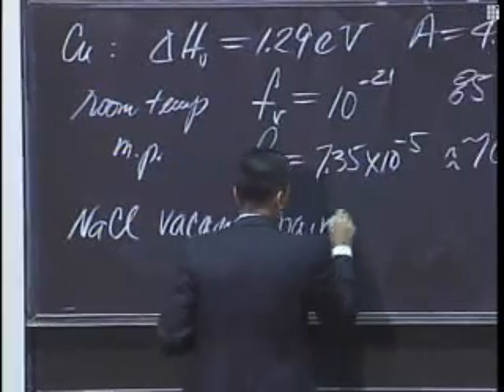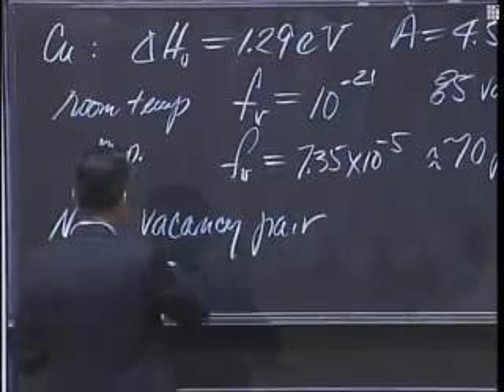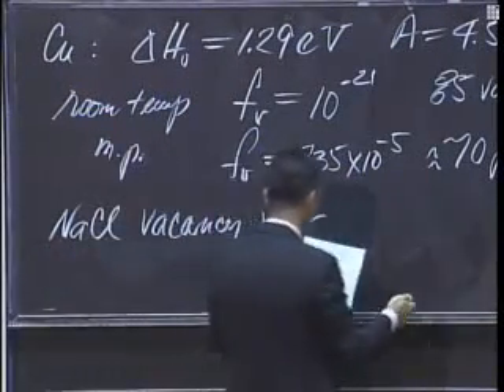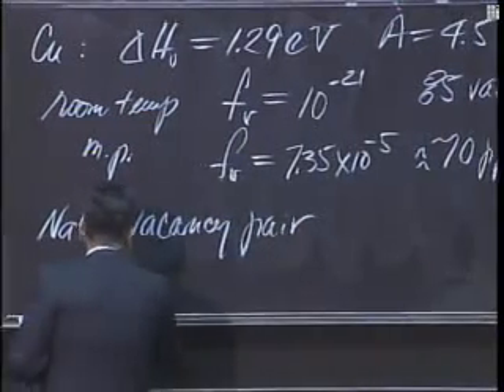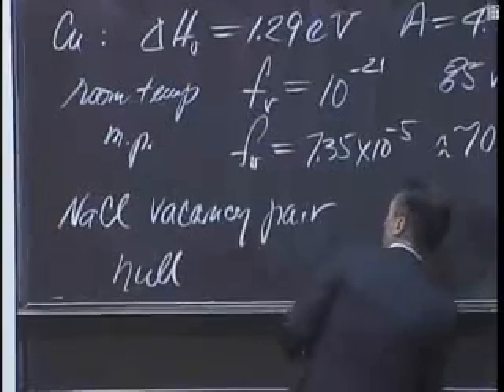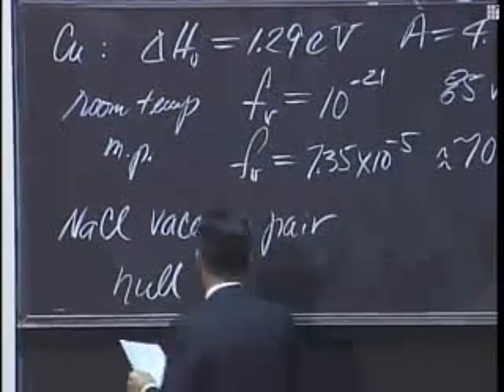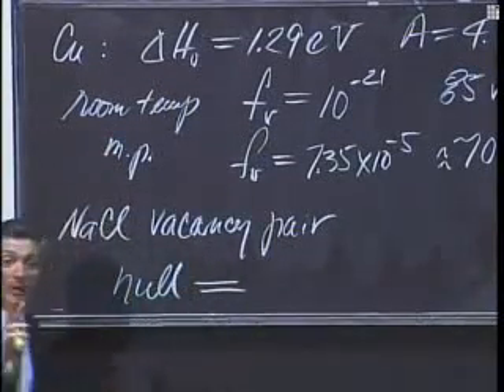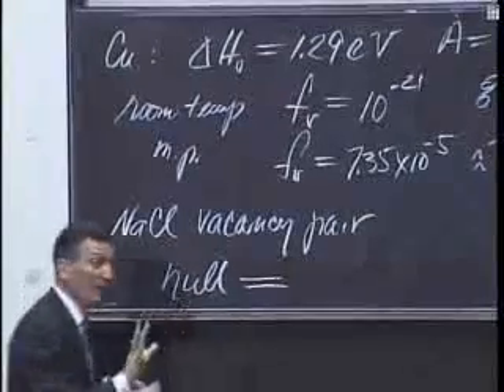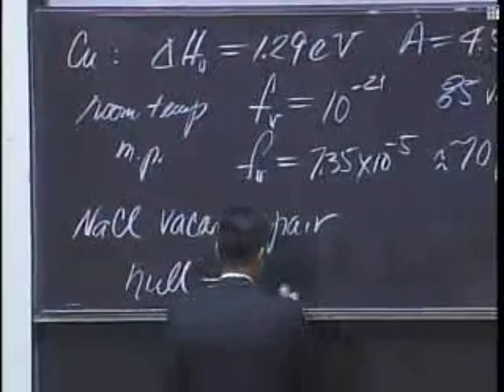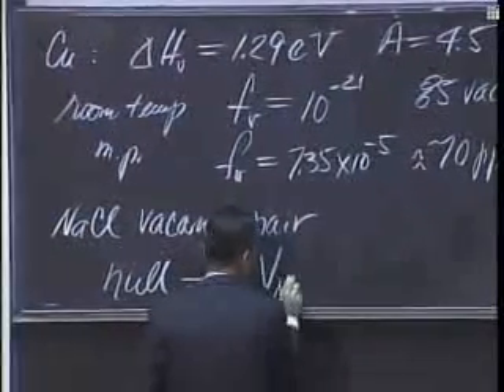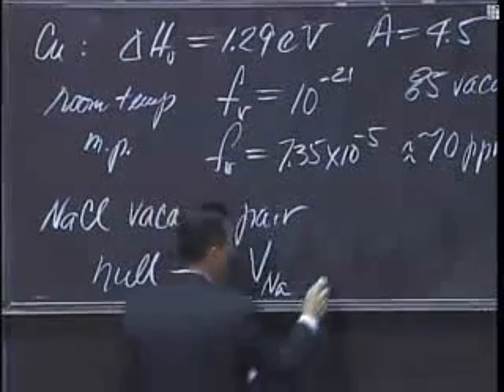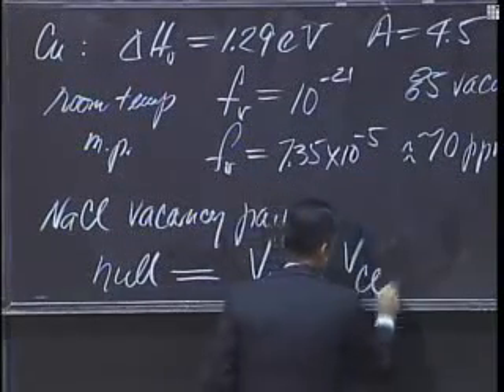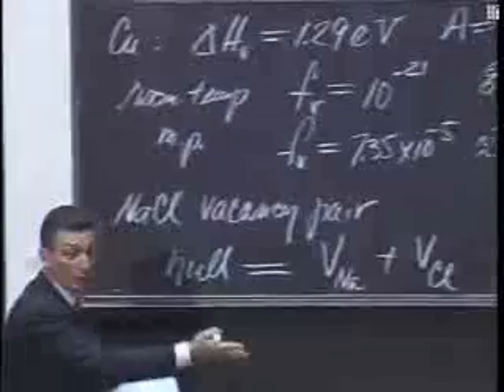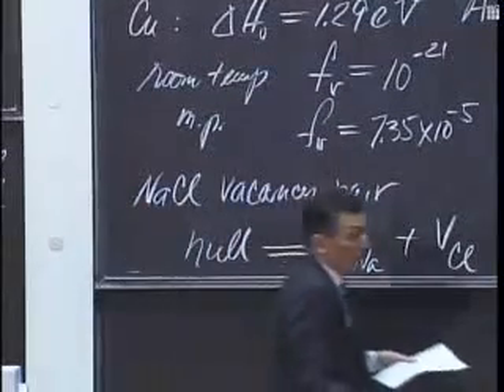So how do I want to make a sodium chloride vacancy pair? Instead of ripping out a sodium and ripping out a chloride, what I do is I take nothing, which I represent as null, and I dissolve it. I'm going to have some nothing that goes to the cationic site and nothing that goes to the anionic site. So this is V as a vacancy on a sodium site and a vacancy on a chloride site. So this is charge neutral now. Okay? We said, well, it's only nothing anyways.